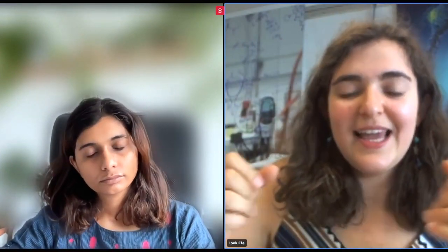growing. And when this material is ferroelectric or polar, let's say, it emits some kind of wavelength. It emits half of the wavelength of what we send. And when we detect that, we can understand what's happening to the polarization while we are growing the film. That's very cool, because usually if we don't have this, it's kind of a black box. We have our growth chamber, we don't know what's happening, we grow something, but we characterize only afterwards. So if we don't see it while we are actually making the material, we cannot control it very well.